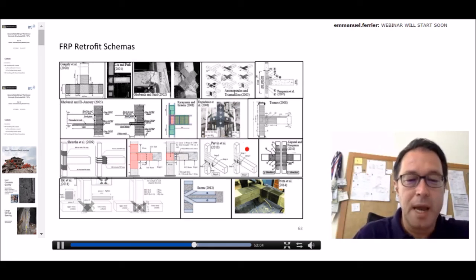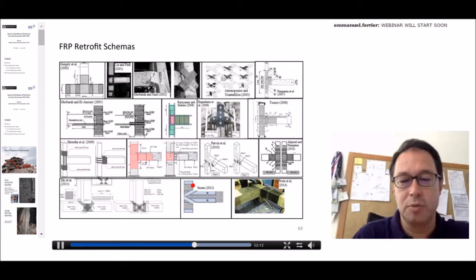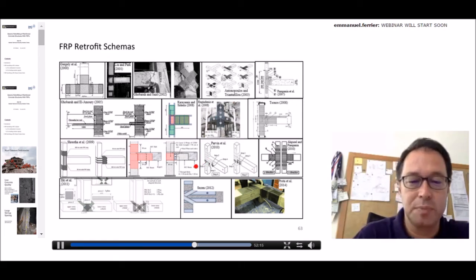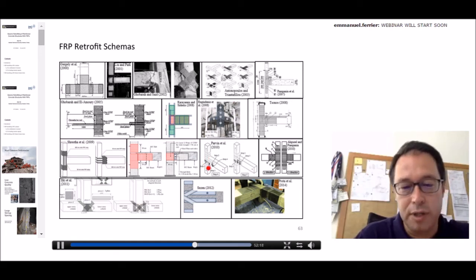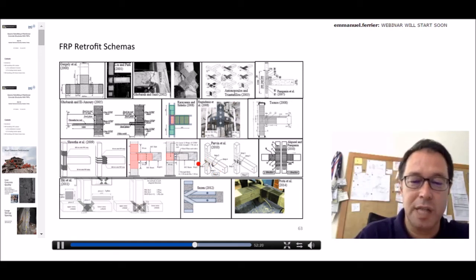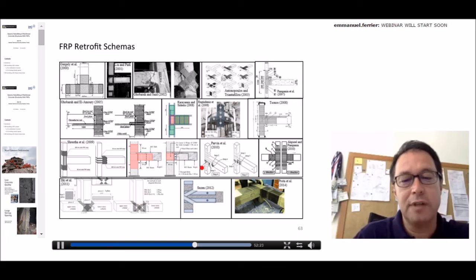Here you see many different types of joint retrofits, but most of them are debatable according to me, because most of them don't include transverse beams framing into the joint, or they don't include the effects of the slabs mostly. So when you don't have these, firstly the behavior of the unretrofitted specimen is underestimated, and also the contribution of FRP to the joint behavior is overestimated. So you can have significant enhancement in behavior, but it's really questionable whether this would be the same in case of field structures.